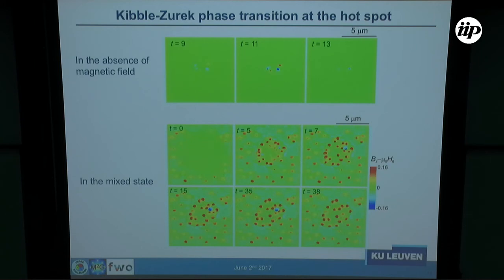Unfortunately, we did not observe this experimentally. Probably the reason is that the pinning is not strong enough in our sample to stabilize them. We are still working on trying to stabilize the vortex and anti-vortex, for example by applying current through the sample, so that the vortices and anti-vortices experience the Lorentz force in opposite directions and we are able to separate them.